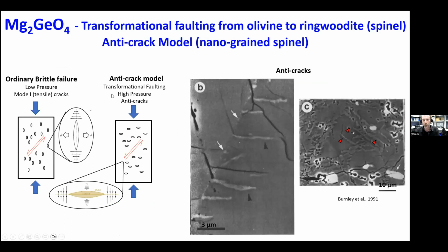Now, they came up with a theory where, in the ordinary brittle failure that I talked about before, you're generating these tensile cracks, you're opening up these cracks that have stress concentrations at the end and they grow. And what they found, if you look on the right, this is spinel here in these lens-shaped kind of morphology. And they said, well, these lenses act similar to these tensile cracks, but instead you have a reduction in volume, and then you have an anti-crack. So it moves inwards, but stress concentrations at the edge cause the spinel to grow outwards. So you have a similar situation as ordinary brittle failure, where these anti-cracks take the place of tensile cracks.